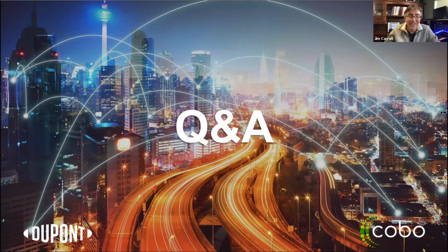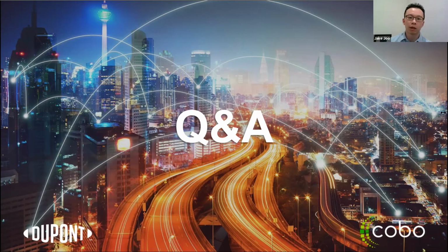Okay, all right, great. Jake, some questions for you too. Yep. So first, has there been an effort to build a BCB cyclotene waveguide for coupling light between a waveguide and a standard SMF-28 optical fiber? At the current stage, what we do is really either air versus refractive index matching fluid to see the material behaviors. We have not done a very specific customization as an interface material. There are ways to adjust the refractive index of the BCB material to get closer to glass fiber, but generally the polymer material will not get as close as glass unless you introduce some other ways. So our approach has been going from glass to the polymer fiber, with some other types of material in between to mitigate the loss issues.